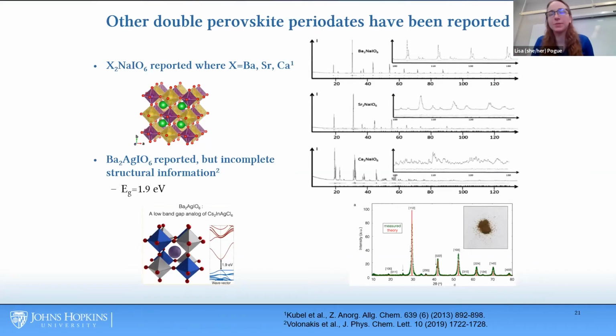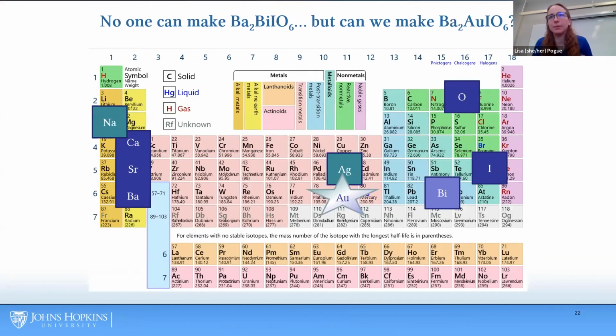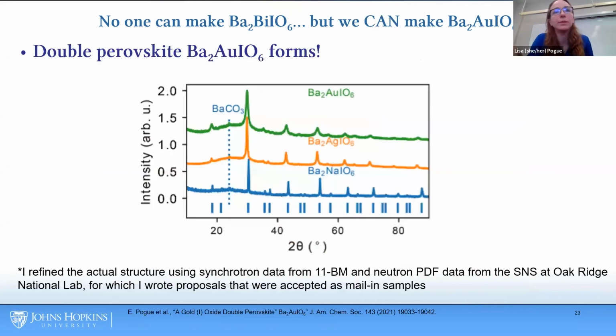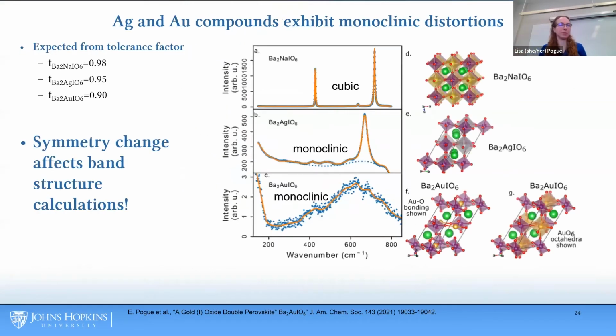There have been other double perovskite periodates that have been reported. And the similarity in these tended to be that the second ion tended to be in the +1 oxidation state, whereas bismuth tends to favor the +3. And so I was looking for atoms that might have large spin orbit coupling that also would be stable in both +1 and +3 oxidation states. And with that, I came upon gold. Barium gold periodate does form. It hadn't been reported before, and so I characterized this phase in much detail.